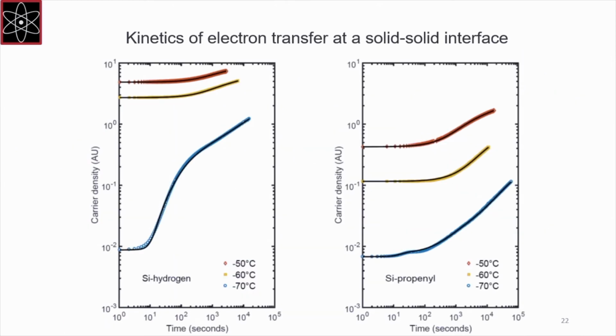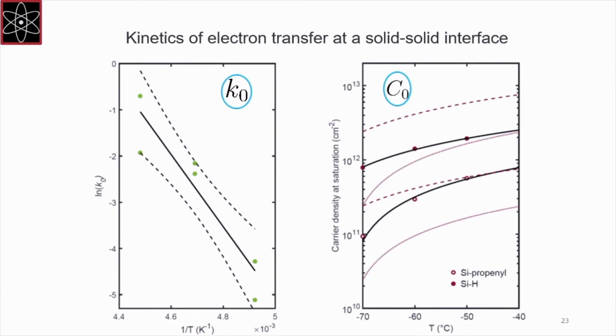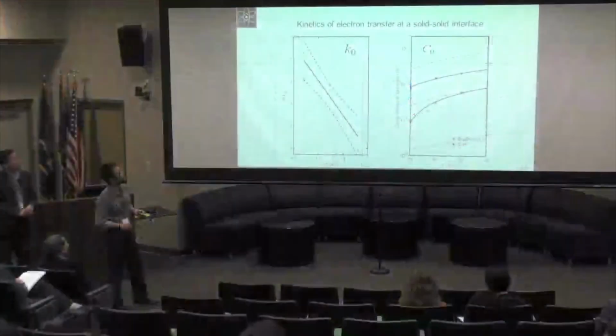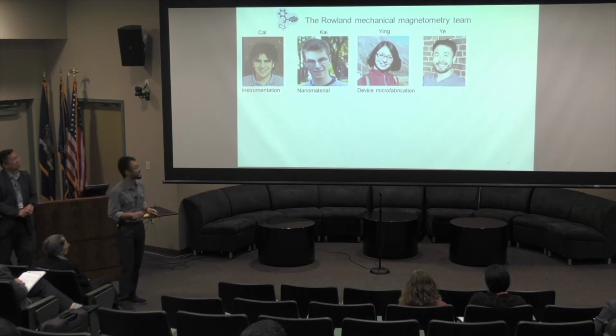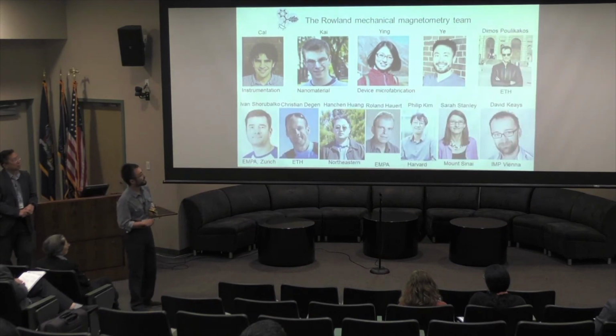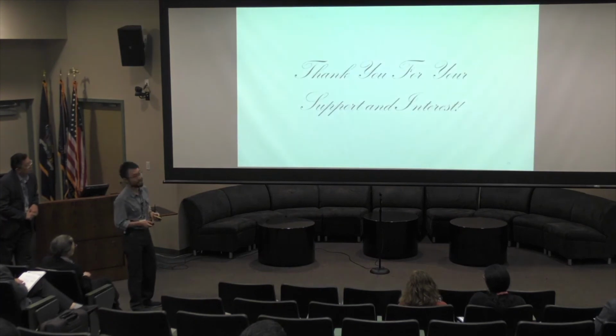And the model was used to fit all data sets in the study and was found to be in quantitative agreement with the data. And from those fitting parameters, we could extract the reorganizational energy of this charge transfer reaction, and also we uncovered a thermal activation effect of a population of charge transfer active species that's a function of the temperature. And with that, I'd like to thank my team at Rowland Institute, the collaborators, and you for your attention.